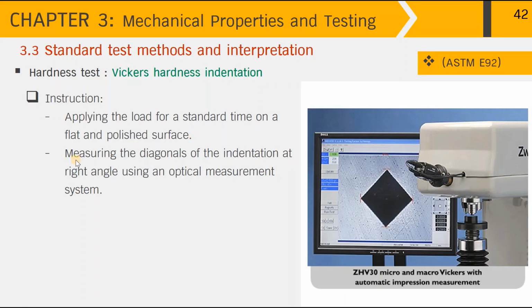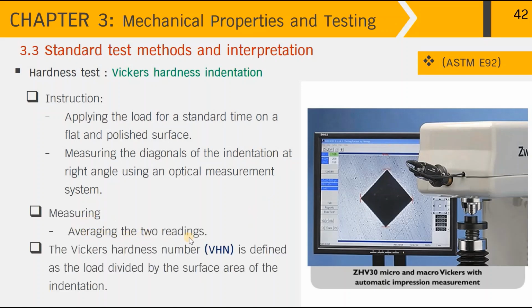And once we apply the load, we have to measure the diagonals of the indentation at right angles using an optical measurement system as shown in this picture. After averaging the two readings of diagonal 1 and 2, we arrive at the Vickers hardness number, with the unit of VHN, and it is defined as the load divided by the surface area of the indentation. And you can see that Brinell and Vickers hardness are roughly defined by the load divided by area, and they are different from Rockwell hardness, where the test data is obtained by measuring the depth of the indentation.